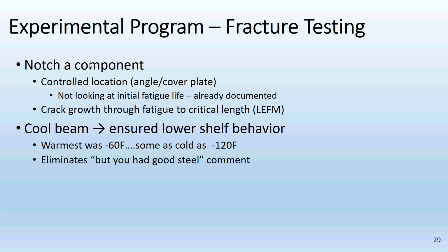And so what we would do is notch the girder, grow it to a critical crack size, cool it, load it up, and nothing would happen. The fracture wouldn't jump. In fact, the individual plate wouldn't fracture. And so we would need to grow the crack more. We would repeat this test, which is very time-consuming, and nothing would happen. In fact, we only had one girder where the component failed.